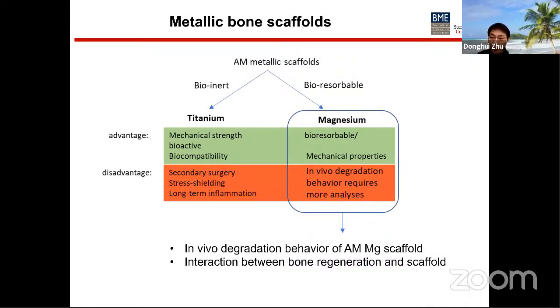Compared to the traditional bio-inert titanium, the bioresorbable magnesium alloy, both have their advantages and disadvantages. For titanium, the mechanical strength, bioactivity and biocompatibility, and excellent osteointegration are good things. But the disadvantage could include revision surgery, second surgery, or removal surgery due to long-term inflammation or the stress shielding effect induced loosening of the implant at the interface.